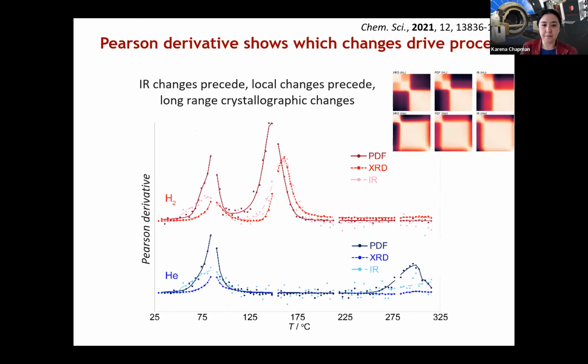And so when we do that for all the distinct different types of data, what then pops out is, regardless of whether we're using the reduction route or just heating it in an inert environment, we can always see the transformation starts in the IR a little bit earlier than what you see in the PDF, and that's a little bit earlier than what you see in the XRD.